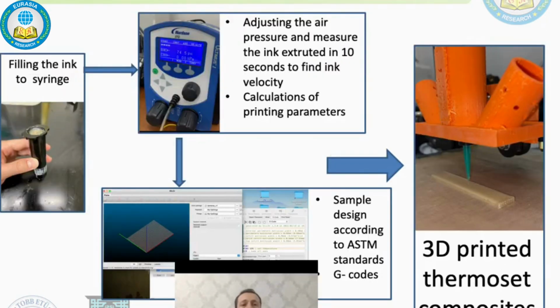fiber reinforced ink. To directly write that composite ink, first of all, we fill the ink into the air adjusted syringe, and after that, we adjust the air pressure and measure the ink extruded in 10 seconds to find ink velocity. After that, we calculate all the printing parameters. Then sample designs are done according to ASTM standards and G codes are generated. After that, 3D printing can be started.